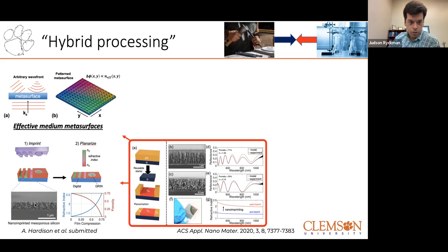So we'll compress our structure, but now we're using a more sophisticated stamp. And so depending on the geometry and the imprint pressure, we can change the refractive index on the surface. So as we compress the film more and more, really the porosity goes down and the refractive index goes up. There's also been some maybe unexpected findings here that the refractive index will not actually return to the refractive index of bulk silicon because there's always a native oxide that's present. So that does reduce the refractive index.